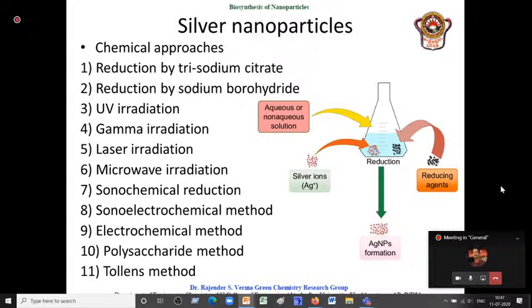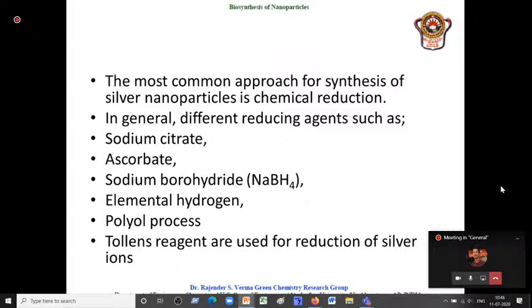They prepared silver nanoparticles, and those silver nanoparticles deposited inside the test tube, and then they look like a silver mirror from outside. See, an ordinary reaction which was just a confirmation test at one particular point is basically a method of preparation of silver nanoparticles inside a test tube. That's how we find this, so that these methods will be helpful for us in understanding that. Okay. So we have a couple of reagents there that we use, maybe sodium citrate or ascorbate, sodium borohydride. We can use elemental hydrogen for reduction, polyols. We can use then the Tollens reagent for silver ions.